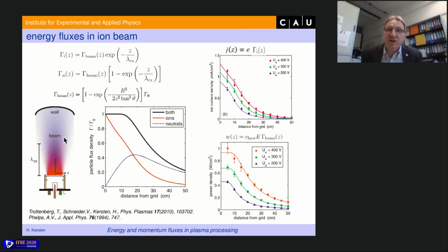And that means we have charge exchange collisions near the ion beam source. We have only ions. But far away, we have only fast neutrals due to the charge exchange collisions. And this is the axial profile from the ion beam source. And that means the ions decrease, but the neutrals increase by charge exchange collisions. And at the end, both contribute to the heating of our probe, both the ions and the neutrals.